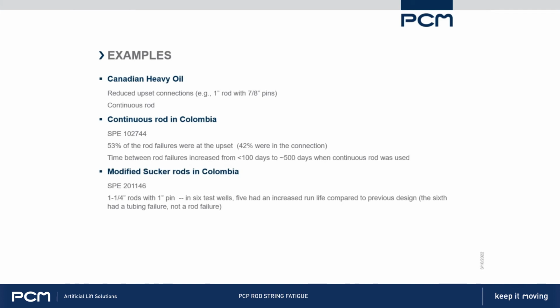So this is the 1 1/4-inch rods with a 1-inch pin, and they modified the pin a little bit to put some more threads on it to improve it for its torque strength. Those modified pins you do not want to use for a beam pump application, though. Adding those extra threads actually makes it worse for a beam pump, but it's very good for PCPs.